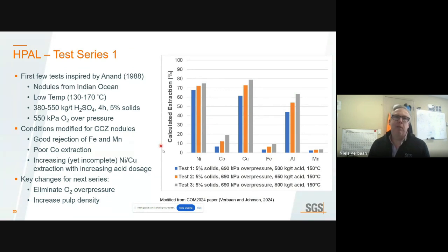So you're going to see some of these graphs here where I'm plotting extraction versus the various metals, nickel, cobalt, copper, and then some of the impurities. And this slide here is our first test series that we ran, and it's trying to copy some conditions that were reported by this author here in 1988. There were different nodules. These were not CCZ nodules. These were, I think, Indian Ocean style nodules. Conditions are listed here. And although we got good rejection of iron and manganese, so low extractions, we liked that. We weren't quite happy with the extractions for nickel, right? We're in the kind of 60s and 70s, even at higher acid addition. So we weren't quite happy with these initial test results.